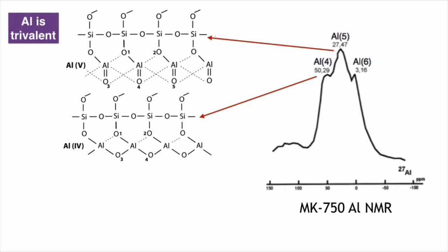For Al4, we have the groups oxygen, aluminum, oxygen, this is the oxide, and the aluminum is surrounded by 1, 2, 3, 4 atoms of oxygen, so it is tetra-coordinated, but the aluminum is still trivalent, and this one, chemically, is less reactive than this one. That is to say, in the alkaline medium, this will react practically immediately, and this will take more time. So we'll have several steps.